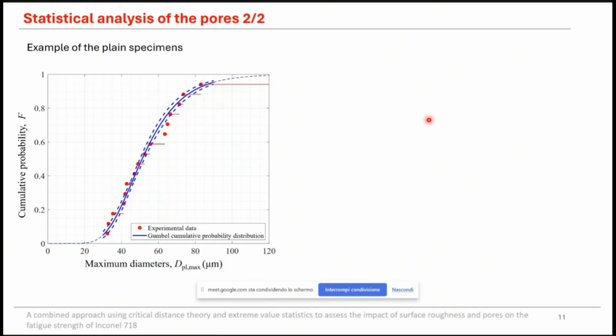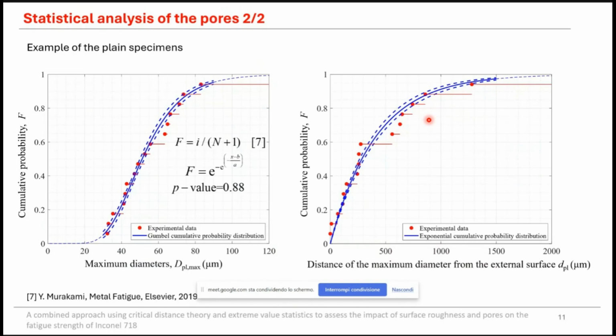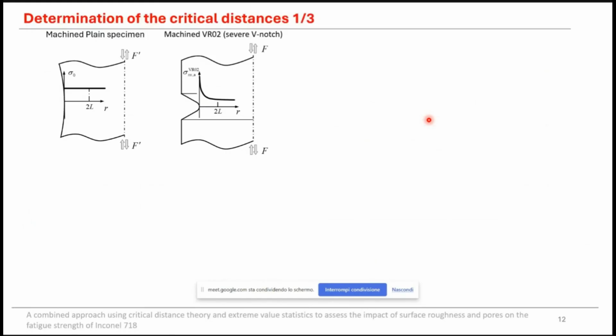In fact, we use a Gumbel distribution function according to the work of Murakami to model the pore diameter, and we use the Kolmogorov-Smirnov hypothesis test on various distribution functions for distance from external surface, and we obtained a high p-value, for example, for the exponential distribution function. Once the statistical analysis of pores was completed, we had to identify the critical distance.